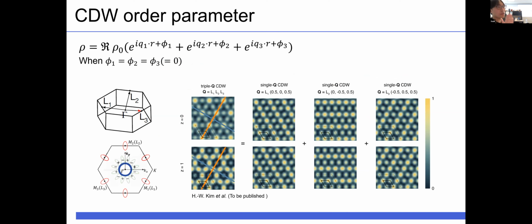So how can inversion symmetry be broken? In order to understand chirality in the CDW, we made a simple model. We know that the CDW is induced by charge fluctuation between gamma points and L points. So we consider the charge density wave along the 3 L vectors in the first Brillouin zone. First, these are plane waves in the first Brillouin zone. And first, we can consider the case that the 3 phases are all the same. Then we can plot the CDW intensity like an STM image, like this. These 2 images indicate 2 layers in the 2 by 2 superlattice. It makes an achiral CDW. You can see the blue line, and you can see that the mirror image by the blue line is identical to itself. It means that it's achiral.